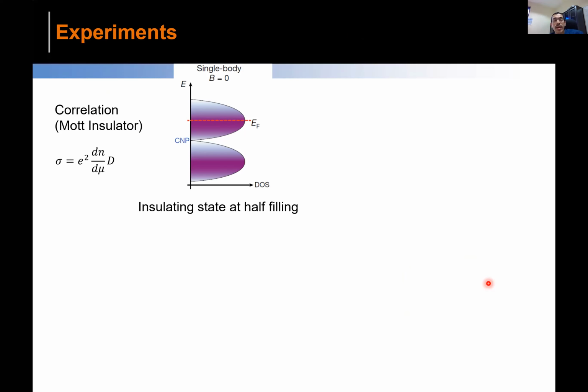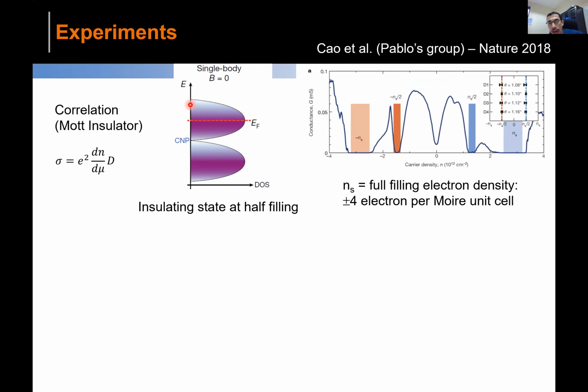Now it brings me to the experimental review of this kind of system, the magic angle twisted bilayer. What I am trying to show you here is energy versus density of states, with the conduction band and the valence band. These are the two flat bands we are talking about, with a very small energy scale, in fact within 10 meV. Now the dramatic thing that happened is this famous paper by Pablo's group, which started this field of magic angle twisted bilayer graphene.